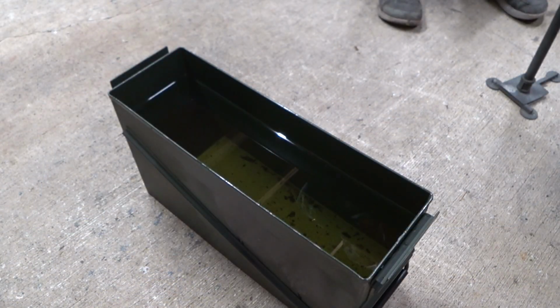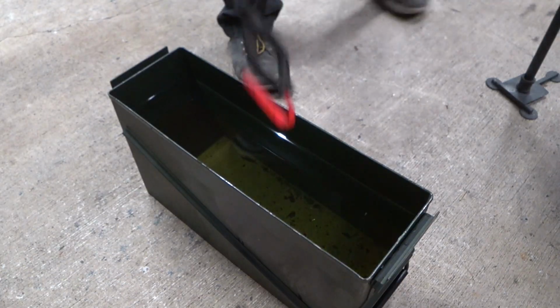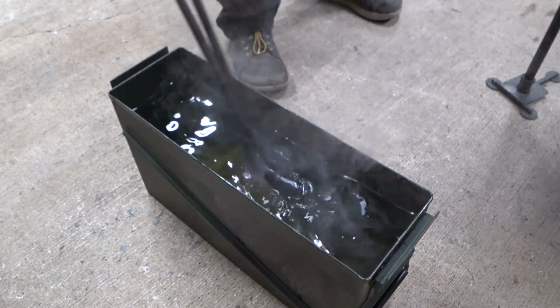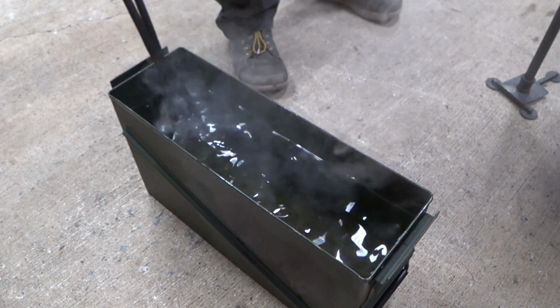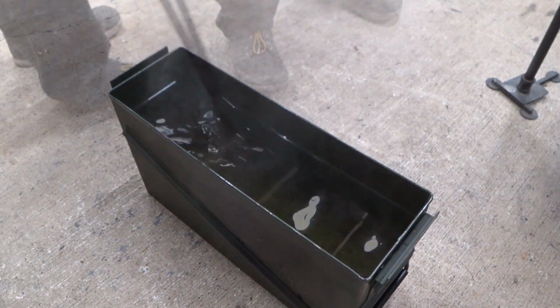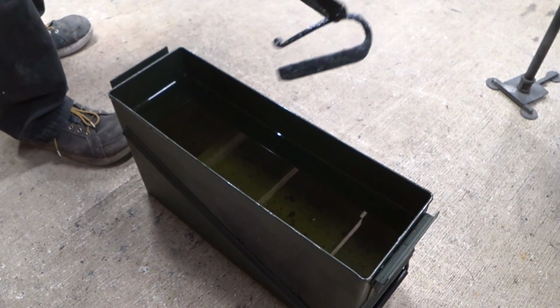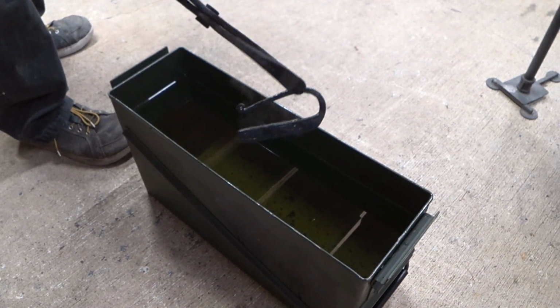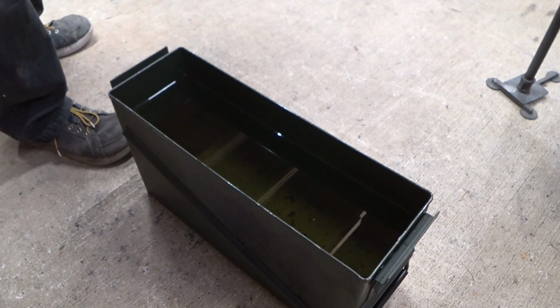The Flint striker was reheated this time to 1500 degrees Fahrenheit, and then we're going to quench in a fast oil. With O1 tool steel, you can use a much slower oil, but all I had was a fast oil available at the time.